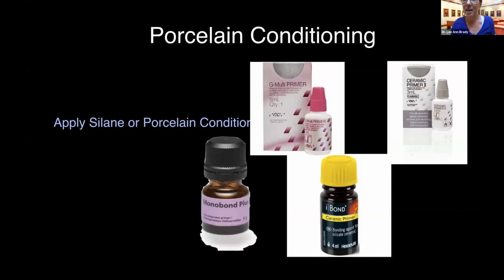How much does MDP increase the bonding for gold and zirconia? Well, there is no other way to bond to gold or zirconia. And so when we talk about bonding restorations, there's 2 bond strengths. There's the bond strength of the resin to the tooth, and there's the bond strength of the resin to the restorative material. And you know, there is no bond between resin and gold or resin and zirconia if you don't etch and then apply MDP. So if you want to bond, you have to use that chemistry. It's the only chemistry that does that.